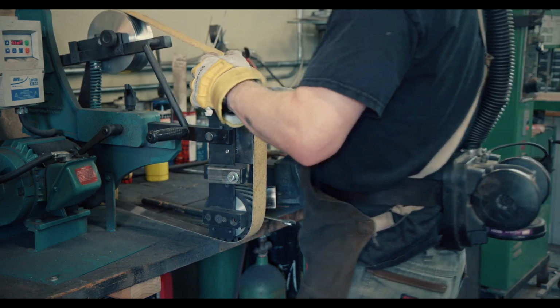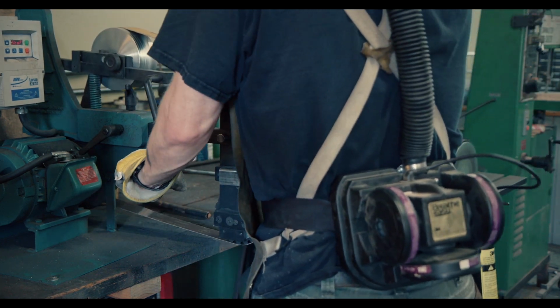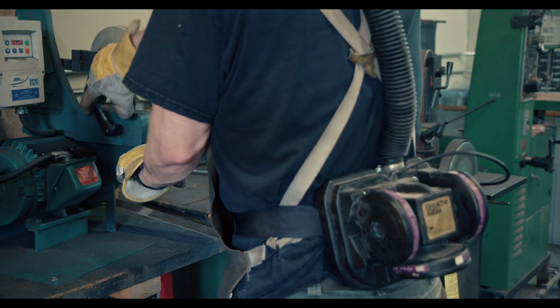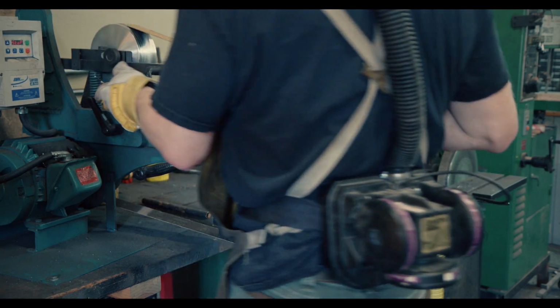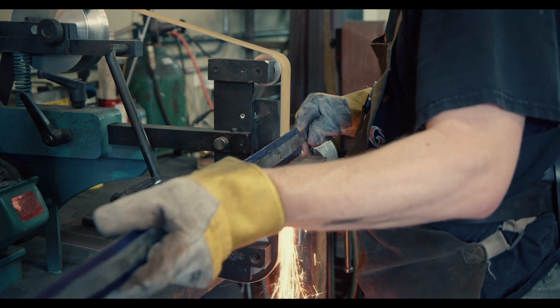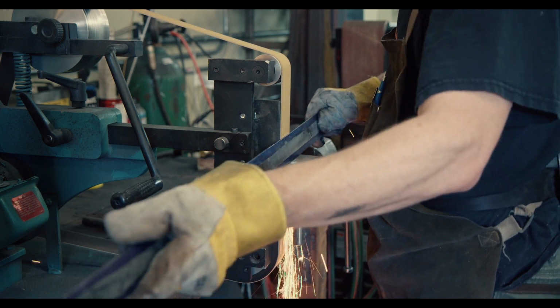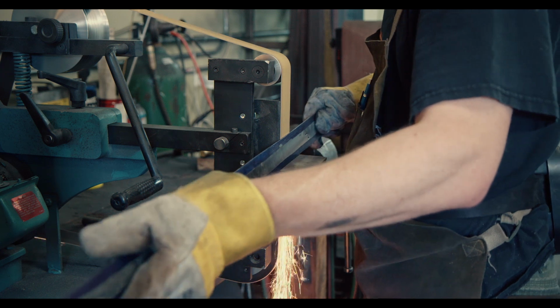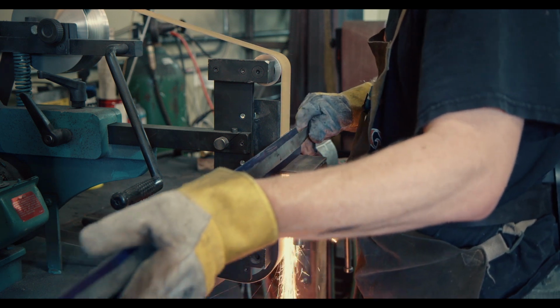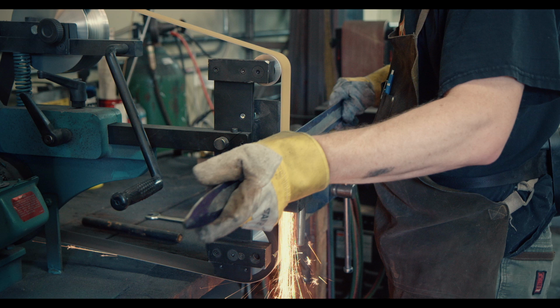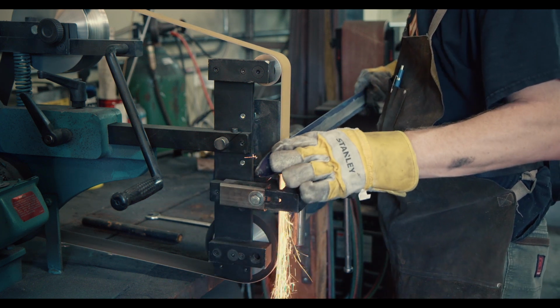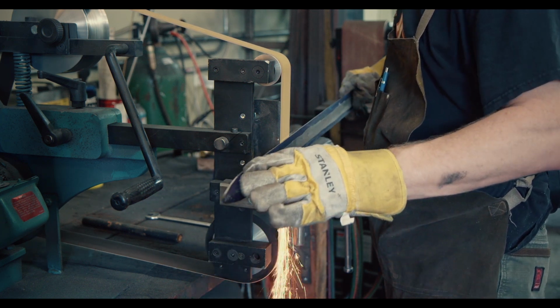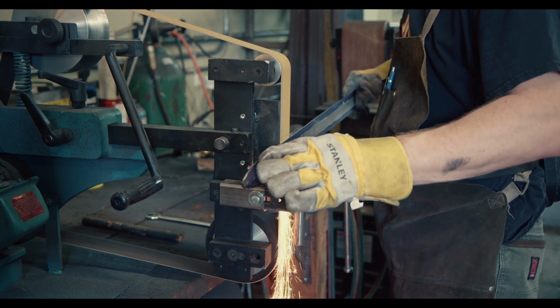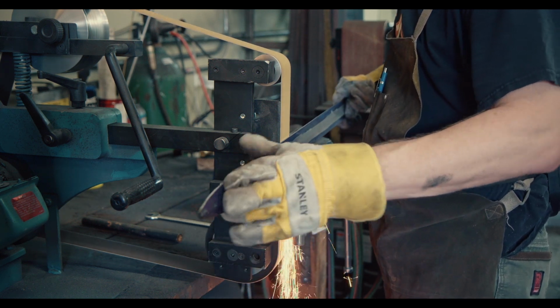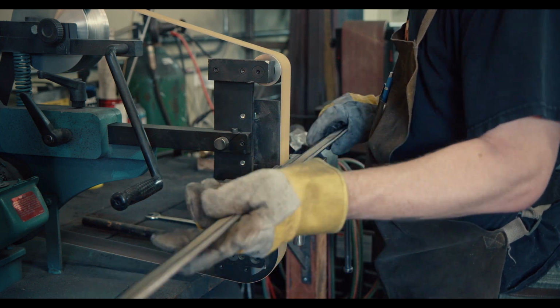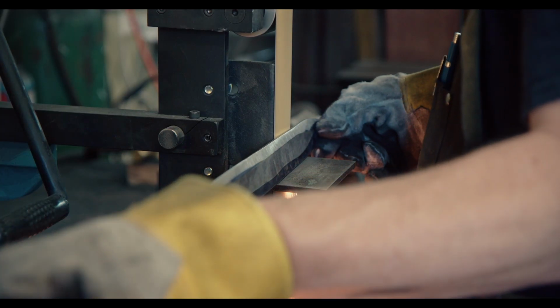Now that I'm reasonably happy with the fuller I created, it's time to grind down the cutting edge. I usually do that on the platen and a small table for support. The table is not necessary, but at least for the initial passes, it makes it easy to aggressively grind down the edge. After heat treating, I usually employ a light touch and may forgo the table. That of course assumes that the sword is going to survive the heat treat. Unfortunately, that is never guaranteed.